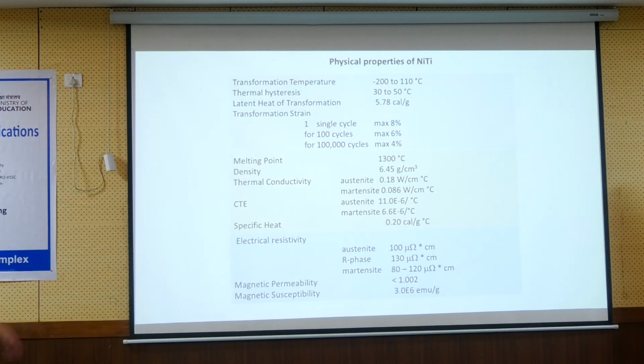And the martensite has lower CTE. Let's say we are making some device like the refrigeration cycle, which we defined yesterday, a refrigeration cycle with the help of elastocaloric materials. It doesn't play much role because the strains are very low. You know, transformation strains are 4%, and this is 0.002%. So it's very small strains. It plays a role only if you are.